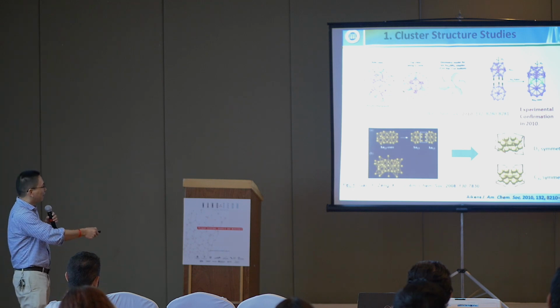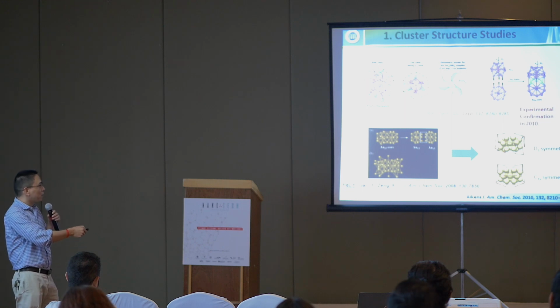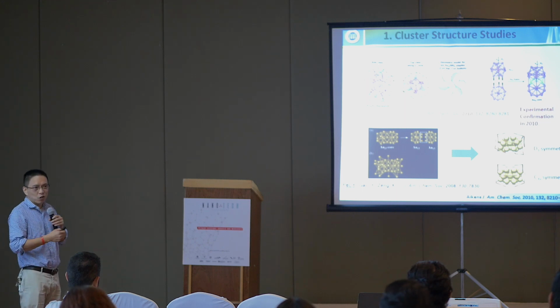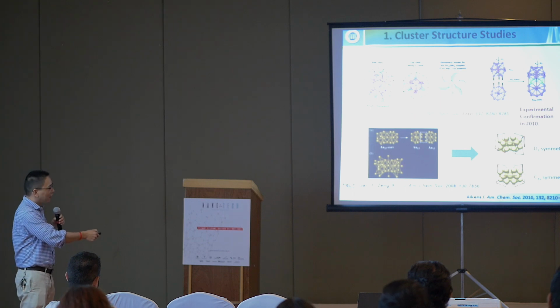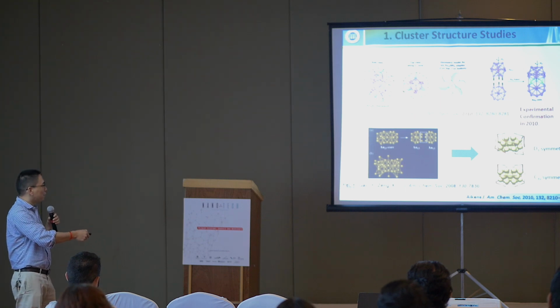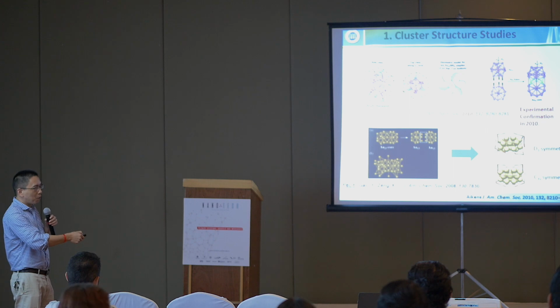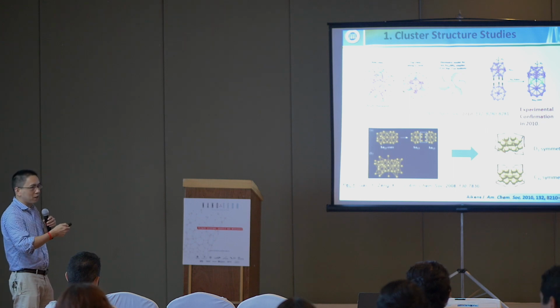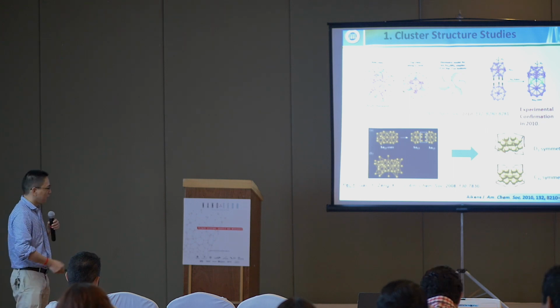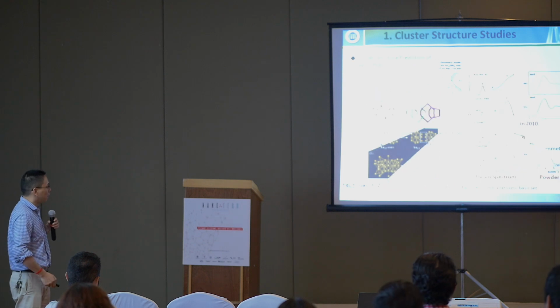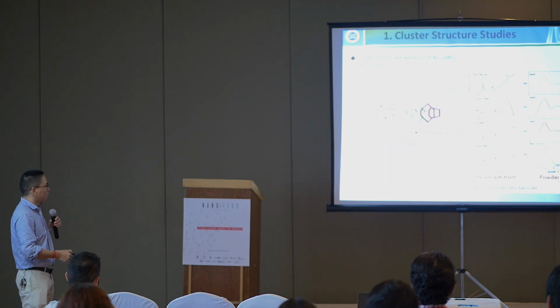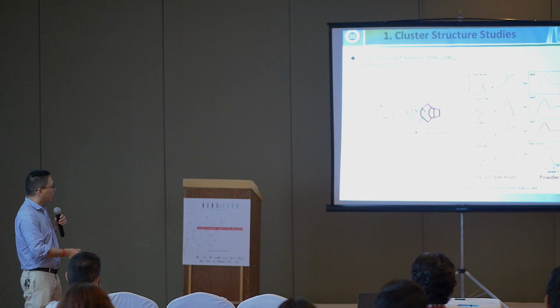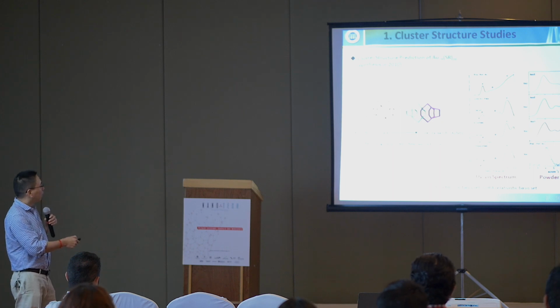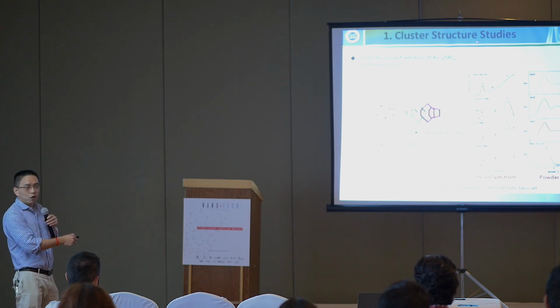The experimental crystal structure was reported by Professor Jin in 2010, and we can see our theoretical model agrees very well with the experimental crystal structure. Okay, this is the first example. And in 2012, we predicted the cluster structure of Au24.